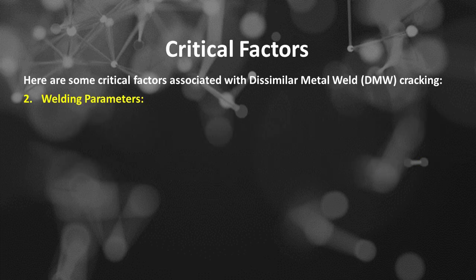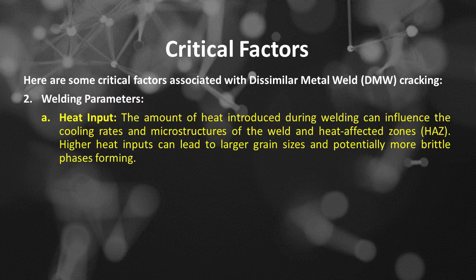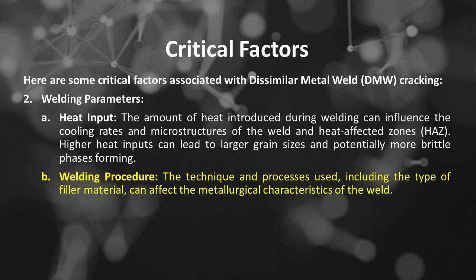Number 2 is welding parameters, such as the following. The first is heat input. The amount of heat introduced during welding can influence the cooling rates and microstructures of the weld and heat-affected zones, HAZ. Higher heat inputs can lead to larger grain sizes and potentially more brittle phases forming. The second is welding procedure. The technique and processes used, including the type of filler material, can affect the metallurgical characteristics of the weld.